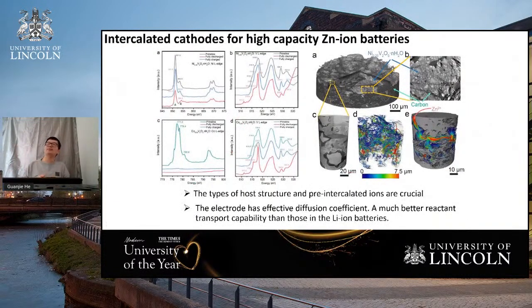And so we also did a lot of collaboration with theoretical scientists, and so also we did a lot of tomography evaluation and the beam time evaluation about our electrode materials. So I won't mention too much technical questions here. And the conclusion with this here is we discussed and discovered the different type of the host structures and the pre-intercalated ions. We find out the different types are quite important for a stable cathode materials in zinc batteries. And our developed electrode materials has effective diffusion coefficient that is much better reactant transport capability than those in the commercial lithium batteries. So from this work, we try to discuss a different cathode host and the importance of the type of species for the pre-intercalated ions in the cathode materials.